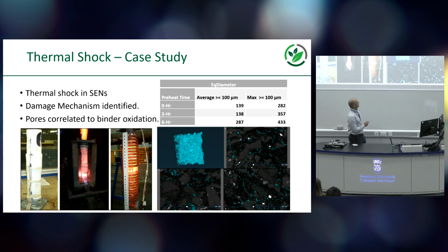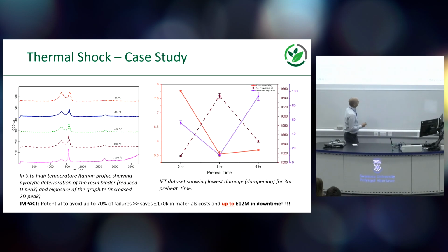So we actually took some of the materials that were being used from those trials and then put them into X-ray CT to look at how the porosity as a function of the damage to that matrix was developing over time, which we're able to chart here. And we complemented that X-ray CT data of the porosity with two other techniques that told us something about why that porosity was developing. So we used both Raman spectroscopy here, which tells us something about the structural differences in the phenolic resin and the pyrolysis of the phenolic resin and the oxidation of the graphite itself by monitoring the relative sizes of this peak here and this peak here, to tell us how that was progressing as a function of temperature and time.